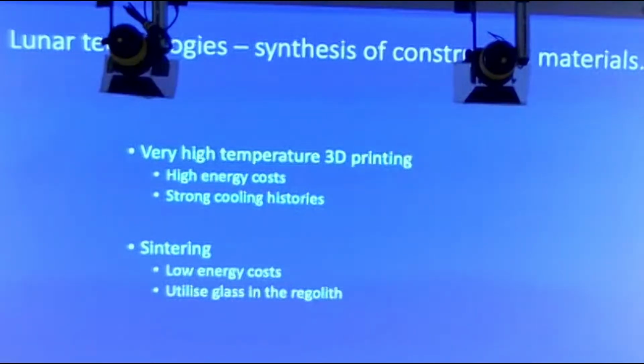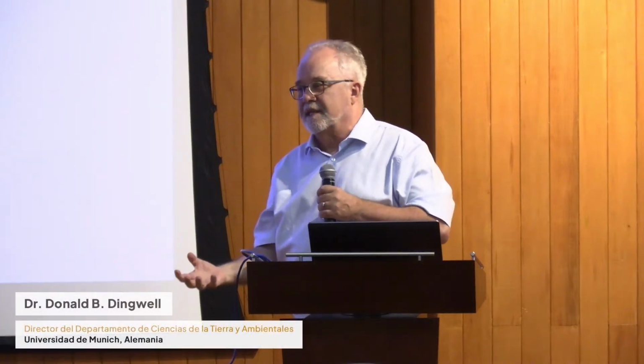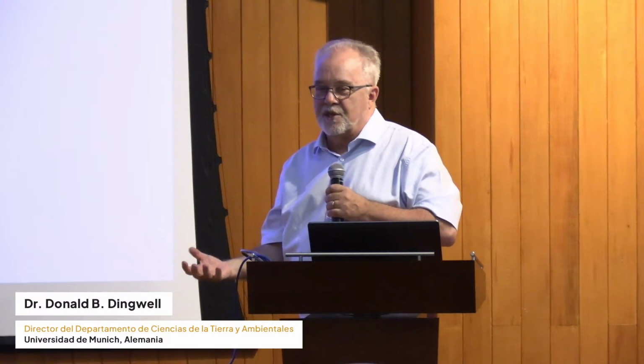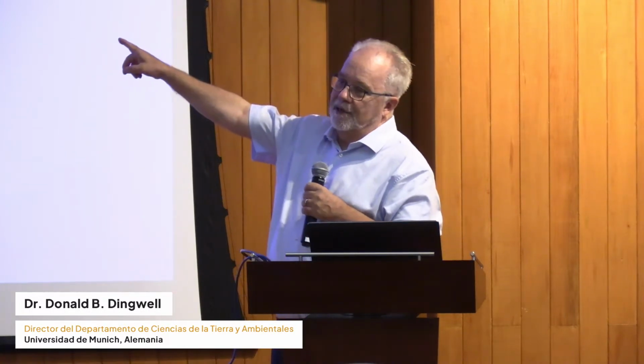It's almost like God gave us what we need here, you know? The glass is what allows itself to be softened and to therefore deform and come into contact with the other phases in the lunar regolith and make a solid. And if you had to heat it up to the point where recrystallization has to do it, or whether you heat it up and it comes down and has to crystallize, it would take much longer and be much more difficult. So the presence of glass in a sintering process drops the temperature fantastically where you have to start. You're down around 600 degrees Celsius versus 1600 degrees Celsius.